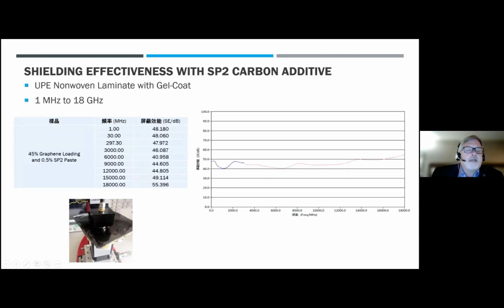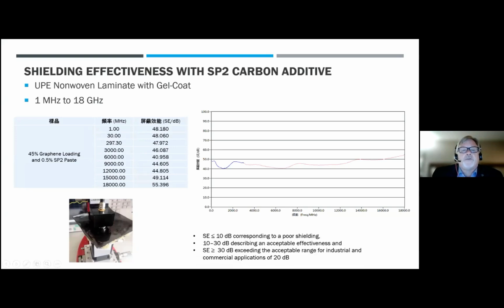So now we take one that's got a little bit less graphene in it, same laminate design. But this time, we're adding that 0.5% of our SP2 carbon paste. And you can see in this graph and in the data in the table where we're now getting well above the 30 decibel range, and we're getting much better shielding in this example. So just by using our SP2 paste, we're helping that graphene to be able to do its job.